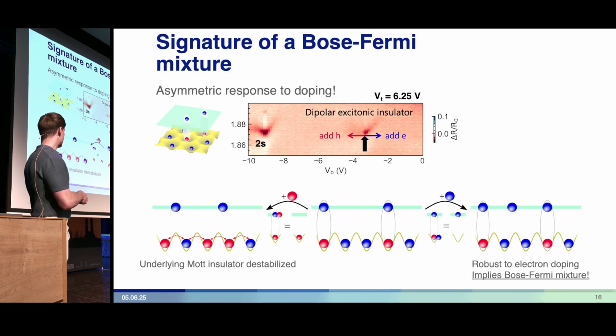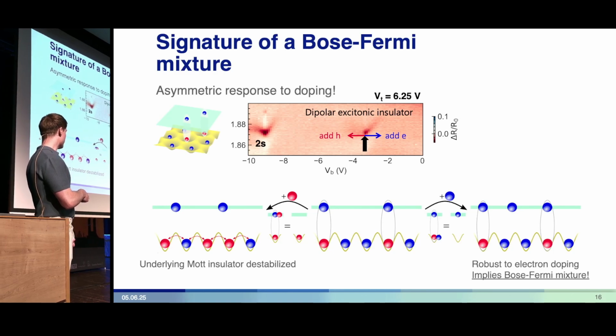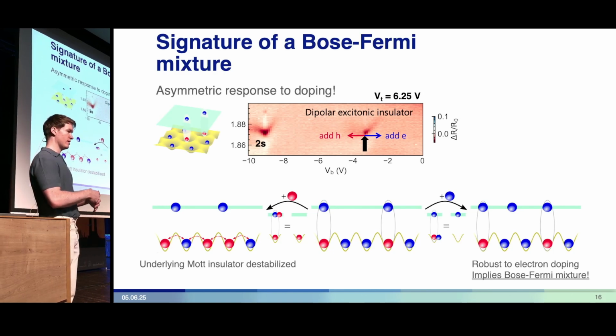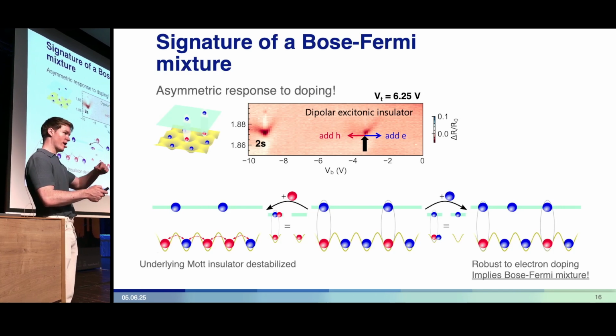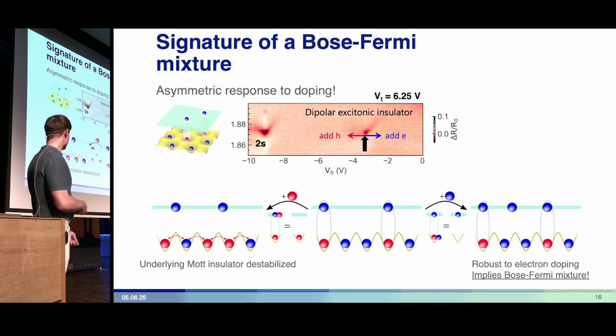On the other hand, if we dope the system with holes, this always results in the liberation of a hole in the Moiré layer, which can then run around wreaking havoc, destroying the underlying Mott phase, destroying dipoles, and this leads to the destruction of the incompressible phase and this asymmetric behavior.